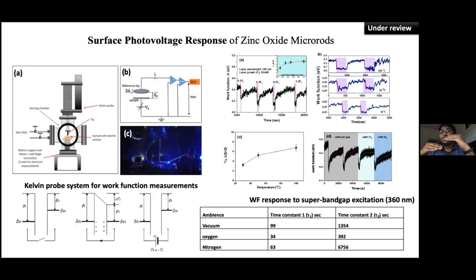Likewise, we evaluate the work function of the sample if you know the work function of your tip, which is a stainless steel tip, for which the manufacturer has given the measured tip work function. We calibrated the system with gold and other standard samples and so on. What we did was, for the same zinc oxide, we excited with super band gap excitation.